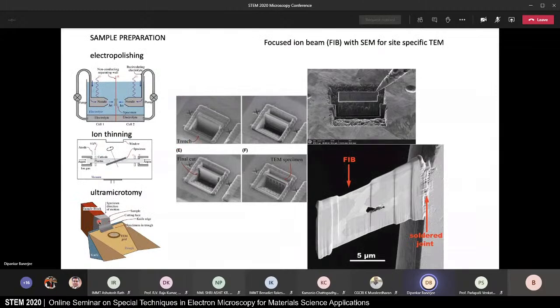Sample preparation is an important part of transmission electron microscopy. Given the energy of the incident electrons, samples have to be transparent to the electron beam. And so your sample thicknesses can usually be no larger than 1000 angstroms, and very often as low as a few angstroms for some of the work in aberration corrected microscopy that people are doing today.